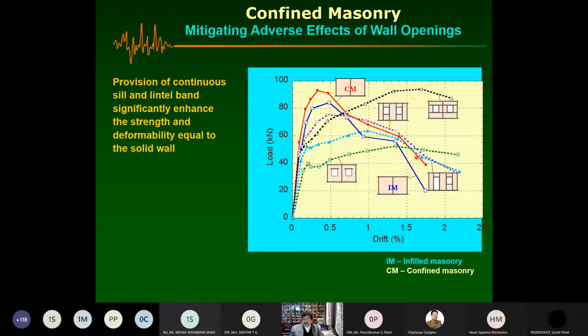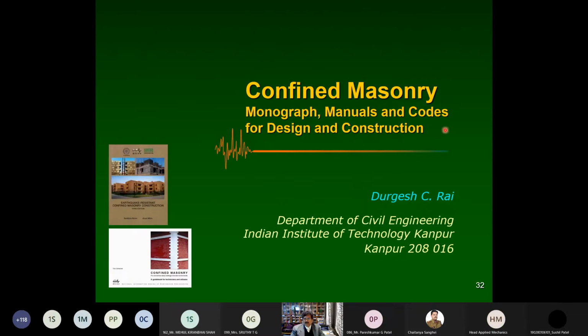Pretty much now you can see the drift levels, which one is dropping, and I'd like you to focus on this infill masonry, which is this blue line here, and the confined masonry with the 2 openings for windows, which is the dotted black line, you see. So it reaches the same strength, and this deformability is what matters. And of course its stiffness is much less because you have the openings, so that causes the decrease in stiffness. And that you can also see with the solid wall confined masonry, which is the red line. So this has a smaller stiffness, but not very different. So these are some quantification of the results, and that helps you in developing the design manuals and codes.